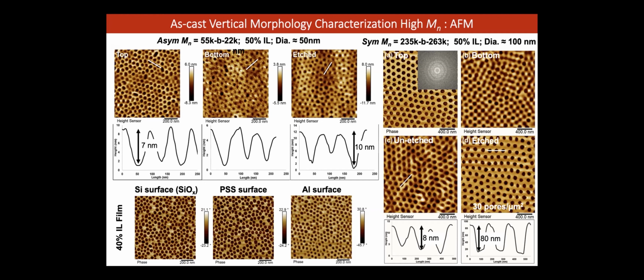And there's a lot of work we did. We published several papers actually with Joe and all, showing that if you vacuum anneal them at elevated temperature, you can even eliminate the ionic liquid. So you add the ionic liquid, get the structure you want, and then you can volatilize it at low pressure, at high enough temperature, which was very surprising.